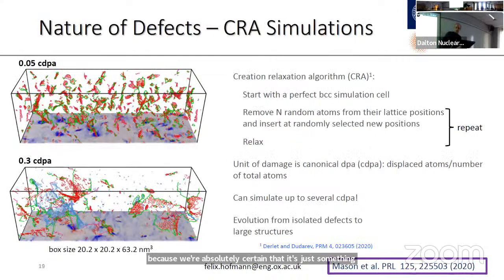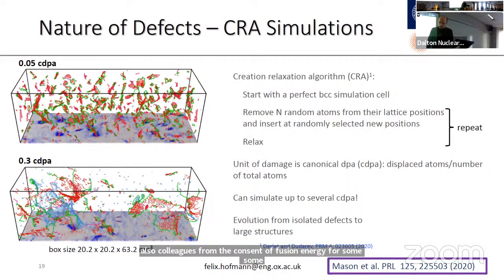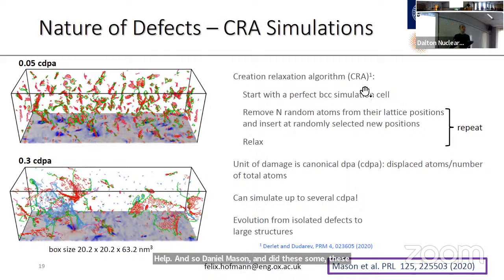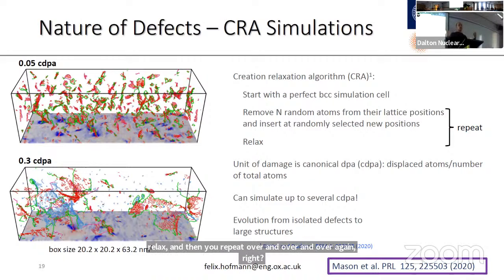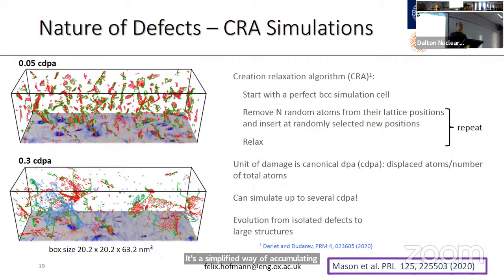So to try and make sense of this, we again asked our colleagues from the Culham Centre for Fusion Energy for some help. Daniel Mason and Sergei Dudarev did these atomistic simulations using the creation relaxation algorithm. The way this works is that you start off with a perfect box of tungsten atoms, pick out an atom somewhere, insert it in a random new position, and relax. Then you repeat over and over again. It's a simplified way of accumulating something that looks a bit like irradiation damage.